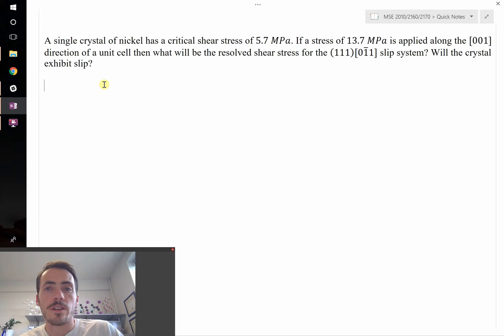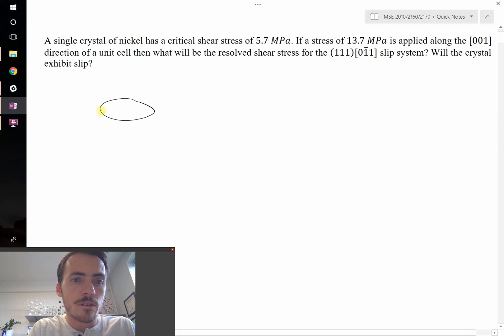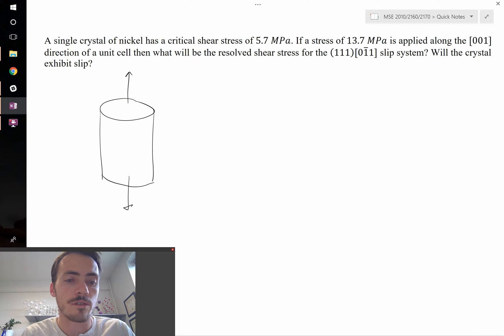This type of question is known as Schmid's Law, and it has to do with the typical drawing that you might have seen that looks something like this. You have a single crystal and you're applying a load in tension. If your slip plane happens to be lined up exactly with it, then it's simple because your resolved shear stress is just going to be the stress that you're applying to it. But in most cases that's not what's happening.